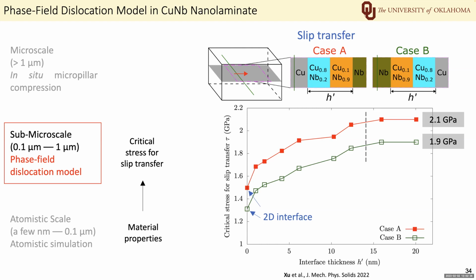I found that, one, the critical stress for the slip transfer is higher for a 3D interface than a 2D interface. And two, the critical stress increases with the interface thickness until about 15 nanometers. After that, the critical stress approaches a constant of 2.1 gigapascal in case A and 1.9 gigapascal in case B.